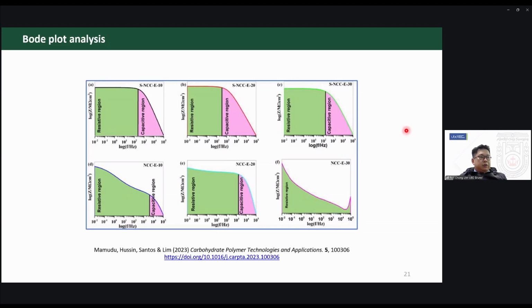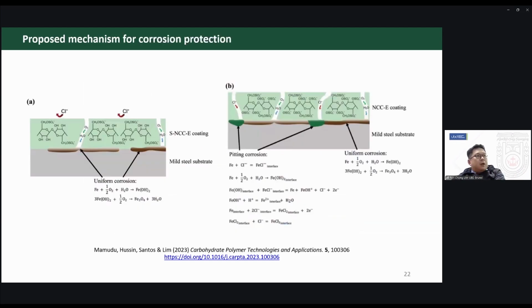And also, I want to make a comment about the capacitive region. So if you have more capacitive region, you also have increased ability to repel corrosive ion species in your coating. So this is actually the hypothesis that we tested in the end.